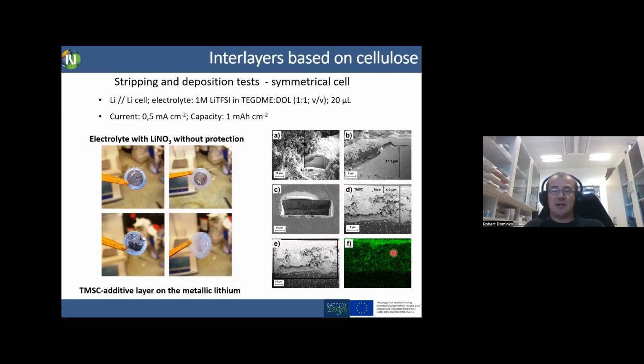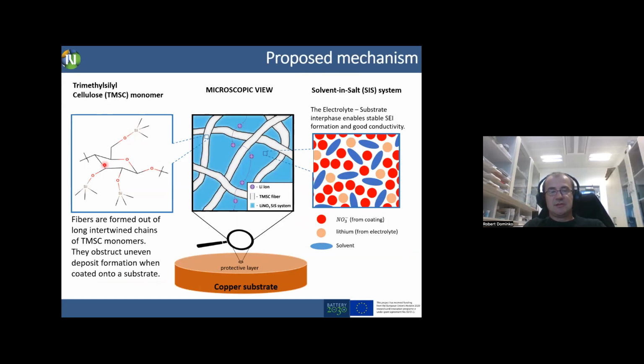which shows that the area was active, but the area didn't create any high surface area lithium on the top. So there was no connection, so there was no penetration through the layer towards the cathode material. And we believe that this is possible because cellulose, at the beginning, was designed to prevent any growth of dendrites because of the intertwined configuration of the cellulose fibers. And with that, we created some kind of network which prevents dendrites.